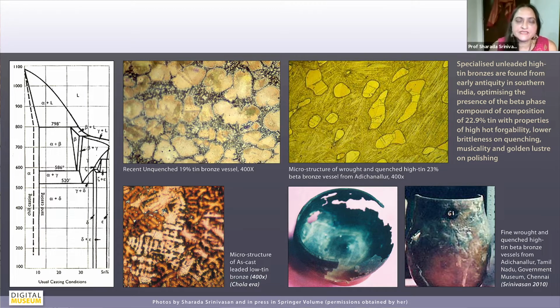And if you look at that phase diagram, which typically plots the changes as you keep adding tin to copper and as you keep increasing the temperature, you see that around 23% tin, at a temperature of about 600 to 700 degrees centigrade, you get the formation of this beta phase. And it seems that they were deliberately aiming for this composition and then hot forging this bronze at a high temperature by repeated cycles of annealing and hot forging. And then what is very crucial is that they were quenching the bronze. Quenching means they were rapidly cooling it down from that beta phase temperature range to the normal temperature.